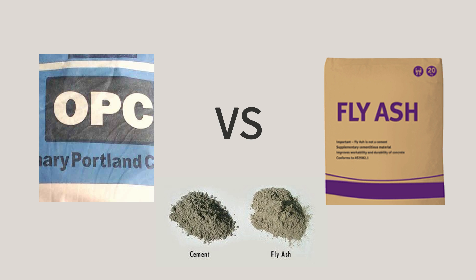We can also mix fly ash at site to save on material cost and also to achieve durable properties due to pozzolanic refinement, but it should be at least 20% by weight of cement.